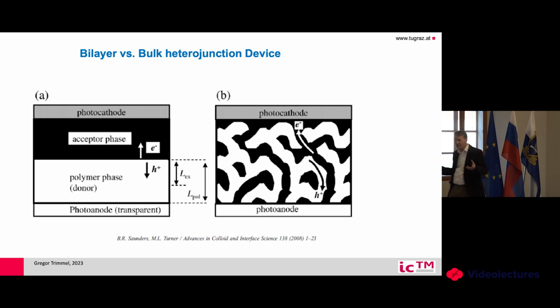So you make a mixture of both to create a larger interface, because the most crucial step is this electron transfer to the other material. And by this, of course, you increase the interface between these materials, and this exciton dissociation, so this redox reaction, is much more easily happening. However, the transport is a little bit more complicated. Here you don't have any problems with the transport. Here, of course, you have much longer ways, and there might also be some isolating materials. So this is the trick in organic solar cells, not only to have good material, but also to optimize this so-called morphology of the solar cell.